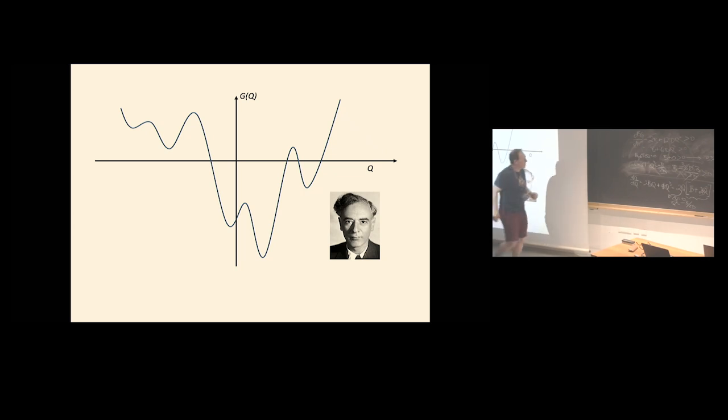Okay. So for the high temperature phase, we've mathematically, trivially, from this pretty blunt version of what the free energy as a function of order parameter might look like, already come up with, number one, a prediction of the high and low temperature state, a prediction of the phase transition. Number two, we've come up with some interesting conditions for the behavior of the prefactor B in front of Q squared.